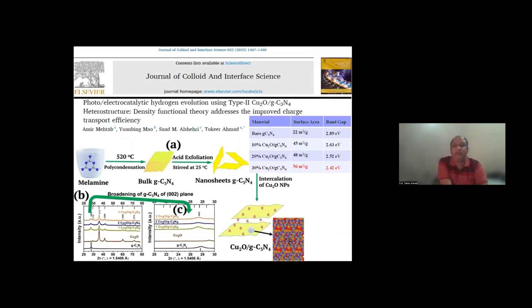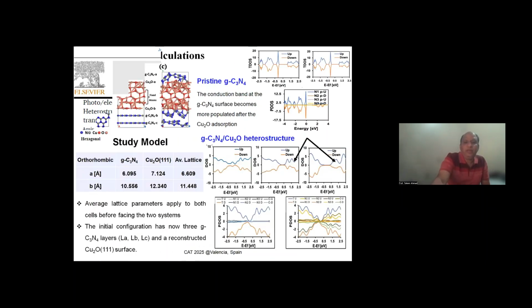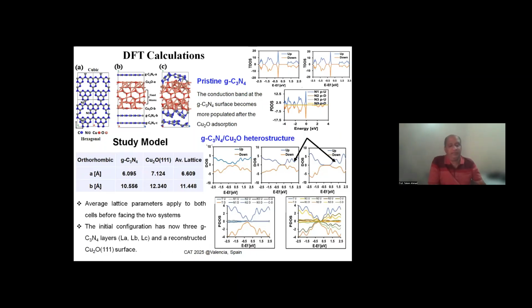Now another binary heterostructure is the copper oxide with the graphitic carbon nitride. Here again, this is also indexed as a type 2 formation. The synthesis protocol, X-ray diffraction, and some data on the surface area and band gap investigations I have presented here. The copper oxide nanoparticles were simply prepared by the hydrothermal method, and then simple mechanical mixing forms the binary heterostructure. If you see the structures of the graphitic carbon nitride and the copper oxide nanoparticle, one has a cubic structure and the other has a hexagonal form. And when you mix both of them, there is a structural transformation with orthorhombic phase formation.